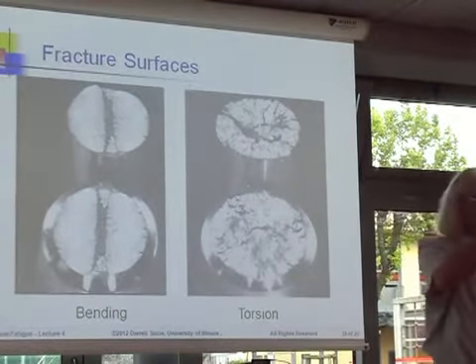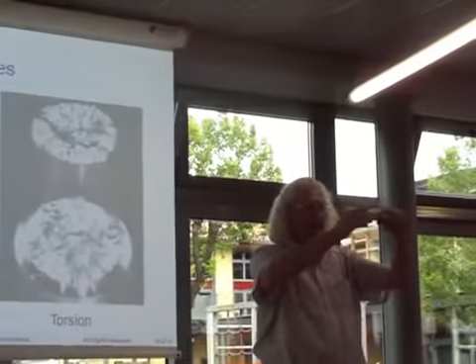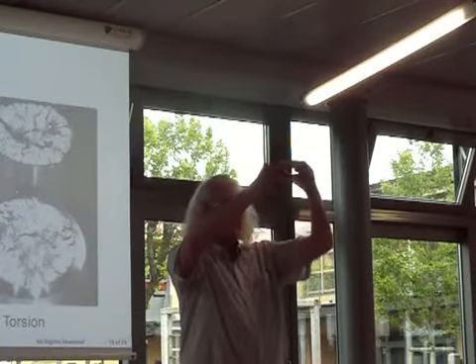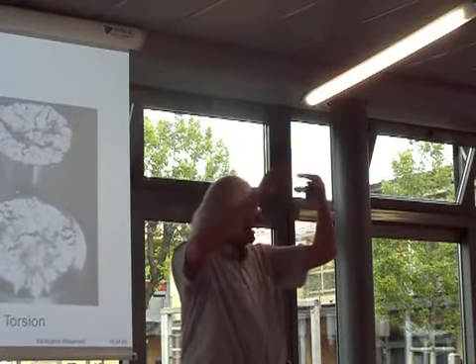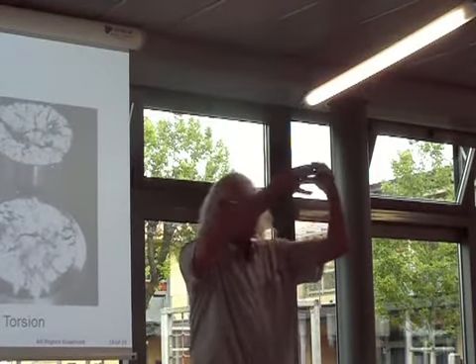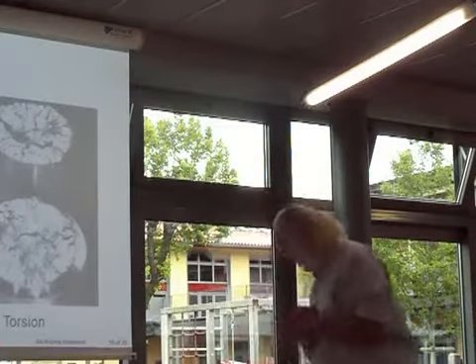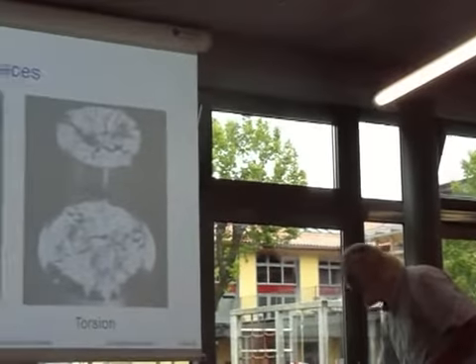Think about it, when this fracture surface is very irregular, I have a lot of mechanical interlocking. So almost all of the force is taken out by mechanical interlocking, not driving the crack. Well, what is the stress intensity for this? How much of the applied torsion is effective in growing the crack? That's the primary variable.